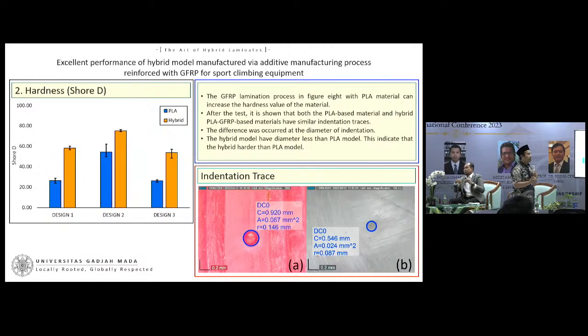Here is the hardness. We can see the hardness is similar to the tensile results. For designs 1, 2, and 3, when we cover the 3D printer models with the hybrid laminates, the hardness is higher than the PLA models. So the GFRP lamination process can increase the hardness of the models.